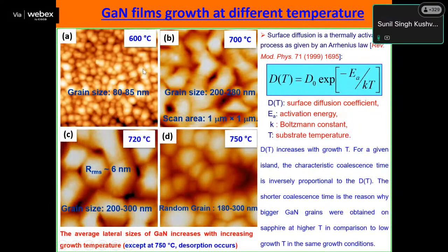When we started with a lower temperature like 600 degrees Celsius, we can see small grain size. Then we grow at the higher temperatures of 700 and 720, and we see the crystallite size increasing. So that is one of the parameters to control, not only the growth rate but also which temperature gives the best result. When we hit 750, again we get a very irregular surface. It means 750 is too high and 600 is too low, so we have to play between 700 to 720 degrees, because we get very large crystallite size compared to 600 and 750 degrees Celsius.